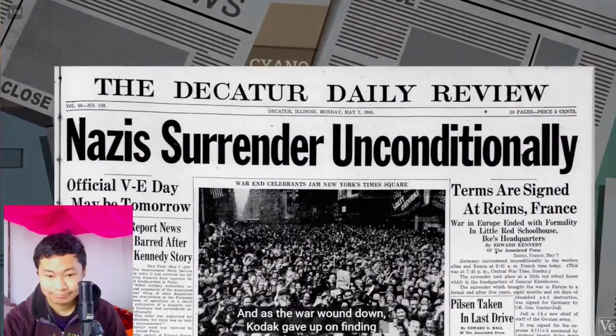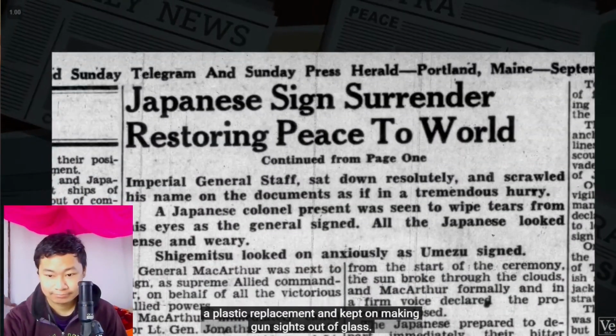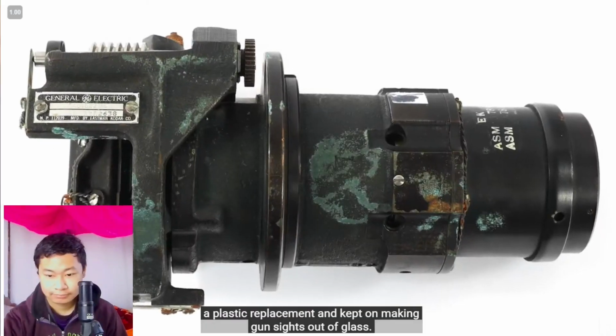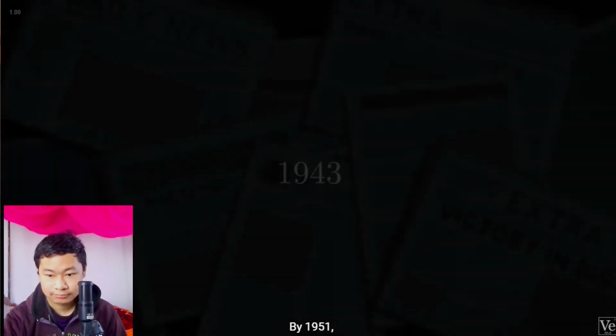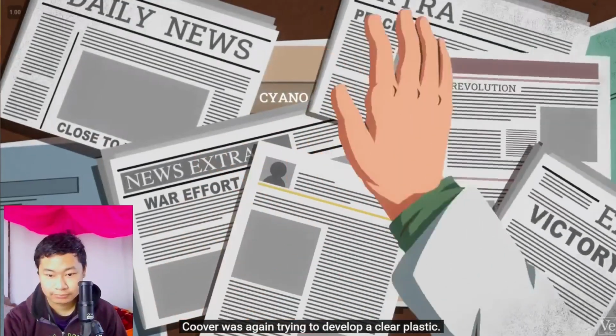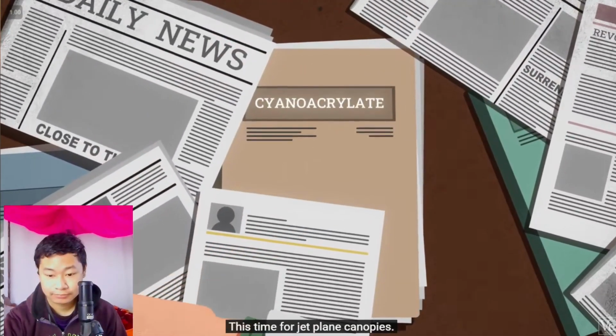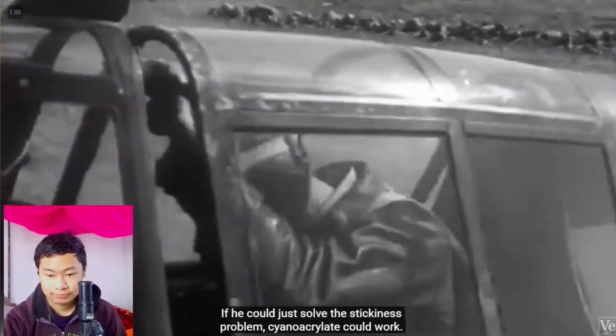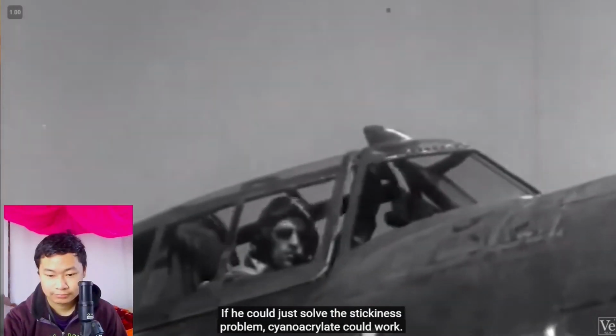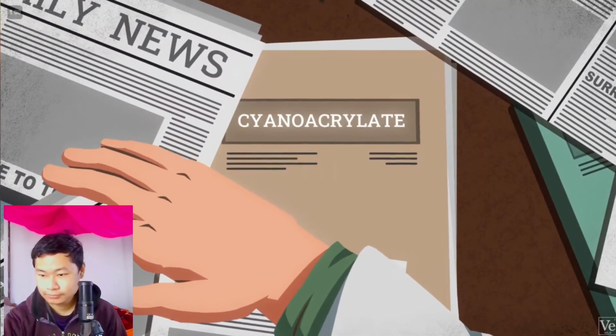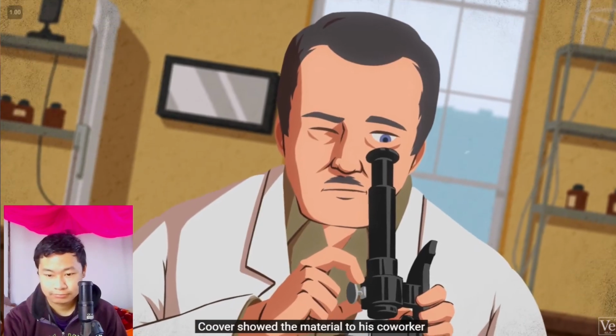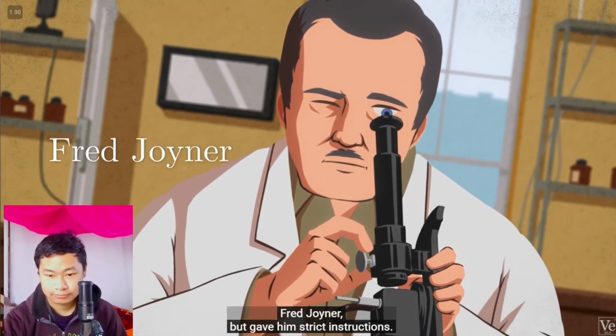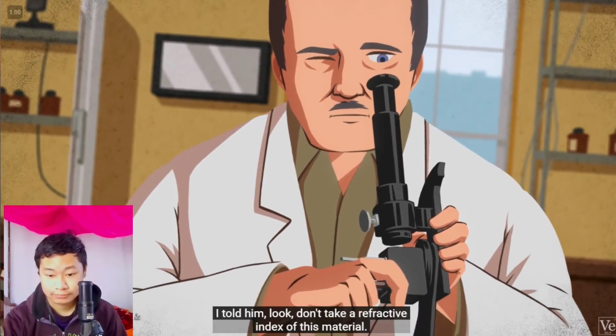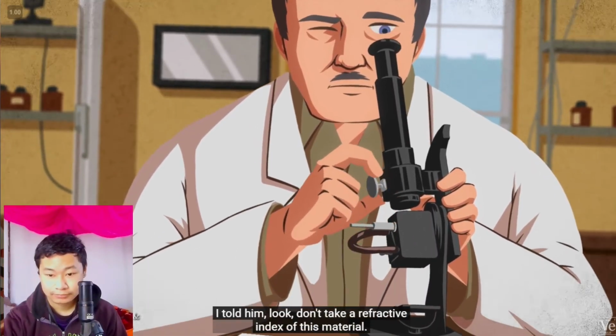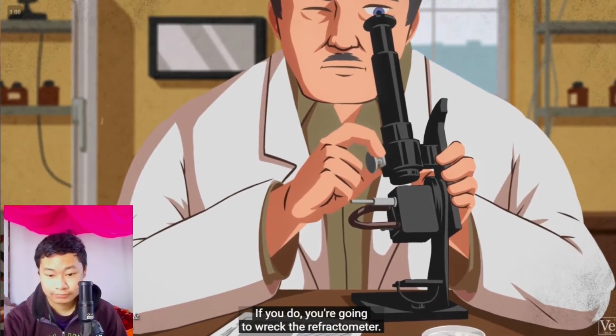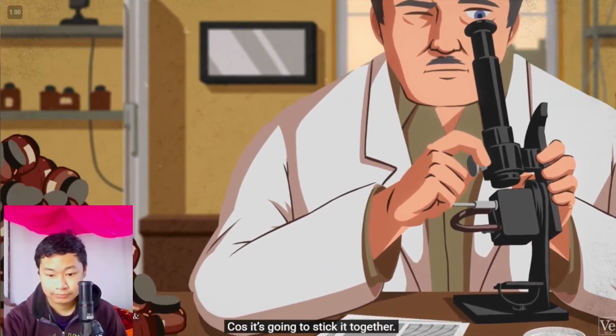And as the war wound down, Kodak gave up on finding a plastic replacement and kept on making gun sights out of glass. By 1951, Coover was again trying to develop a clear plastic, this time for jet plane canopies. If he could just solve the stickiness problem, cyanoacrylate could work. Coover showed the material to his coworker, Fred Joyner, but gave him strict instructions. I told him, look, don't take a refractive index of this material. If you do, you're going to wreck the refractometer because it's going to stick it together.